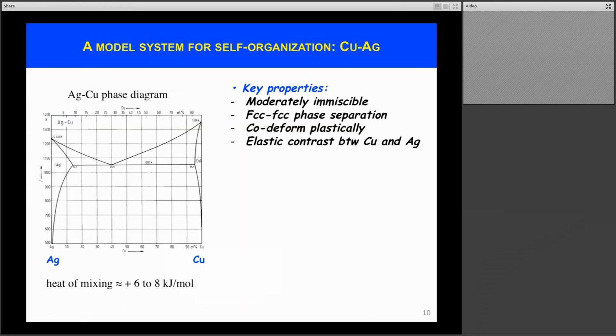So for this, we're going to consider simple binary systems such as copper-silver. So I grab the equilibrium phase diagram of the system. You recognize here a simple eutectic phase diagram. And we're going to work at low temperature, so near room temperature, a little bit above. So we'll be in this region of the eutectic phase diagram where the system should separate into two phases, one that is essentially pure silver and one that is essentially pure copper.